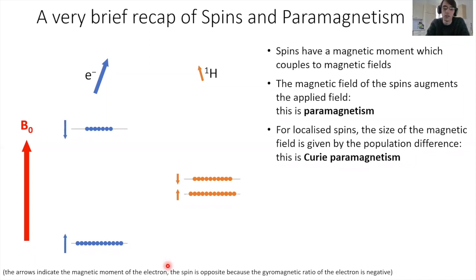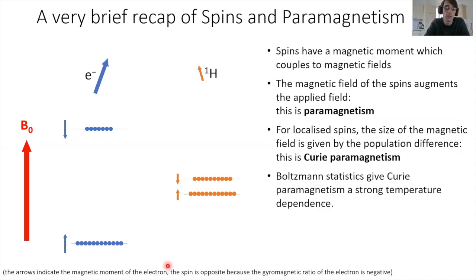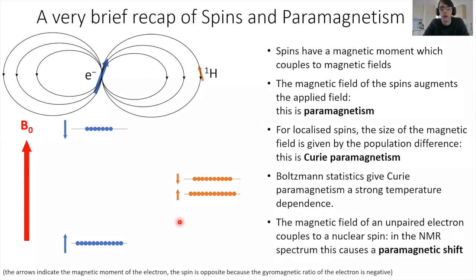And so the size of the magnetic response is dictated by the population, which is given by Boltzmann statistics. So this depends on the energy separation. And so we know that the electron has a larger gyromagnetic ratio, so it has a larger energy separation, a larger paramagnetic response than nuclear spins, which have smaller energy. But the other key factor is temperature. And this Curie paramagnetic response has a very strong temperature dependence. And in particular, you have to go down to very low temperatures to get large paramagnetic responses. The final thing I want to say on the slide is that electron spins can couple to nuclear spins, and in the NMR spectrum, we see that as a shift, and this is known as a paramagnetic shift. And this also has a strong temperature dependence due to Curie paramagnetism.